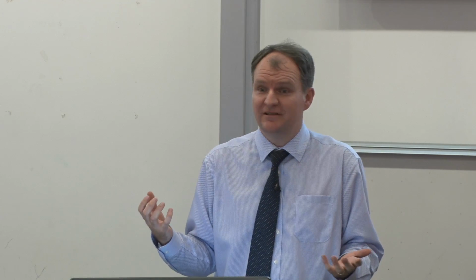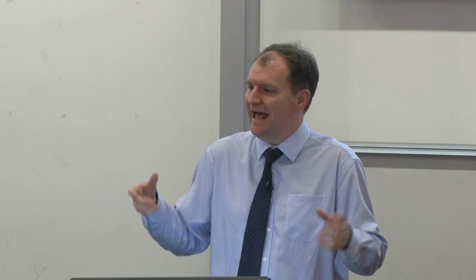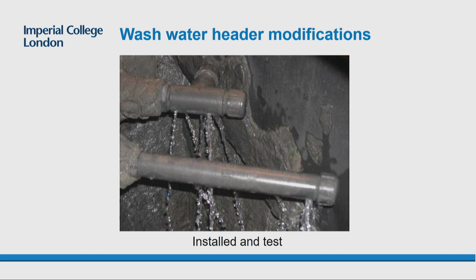So we actually proposed that they do some modifications to this. Catherine did a lot of the calculations for how you change the holes in the system. And so we modified it. The modifications literally consisted of making a few of the holes in the wash water addition slightly bigger and adding a couple of plastic T's onto the system to try and even it out. So this just shows our addition. There are some bigger holes right near the end, and a couple of T's trying to cover some of the blank area. So very, very simple additions and changes.